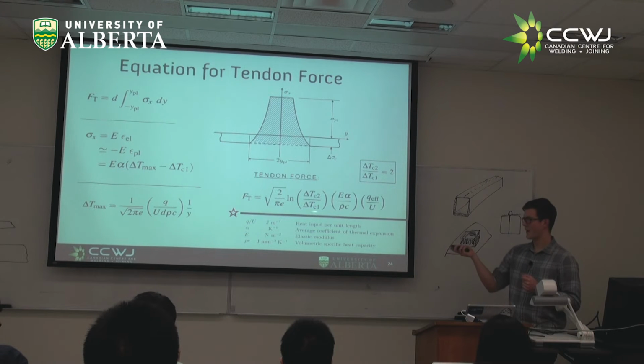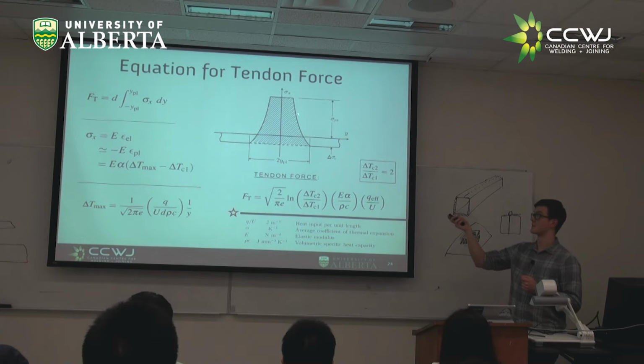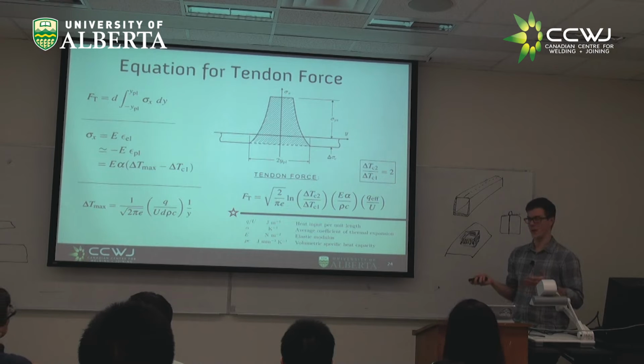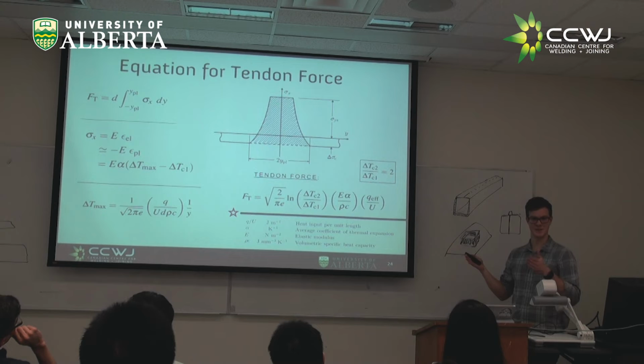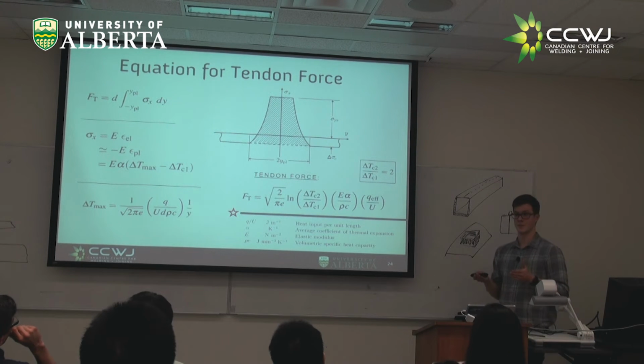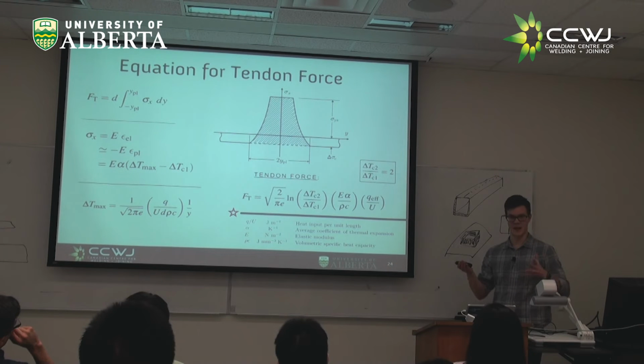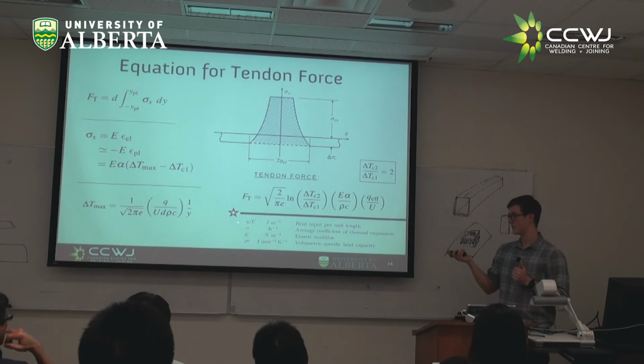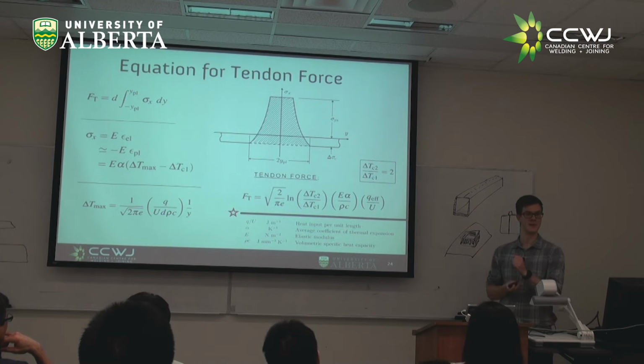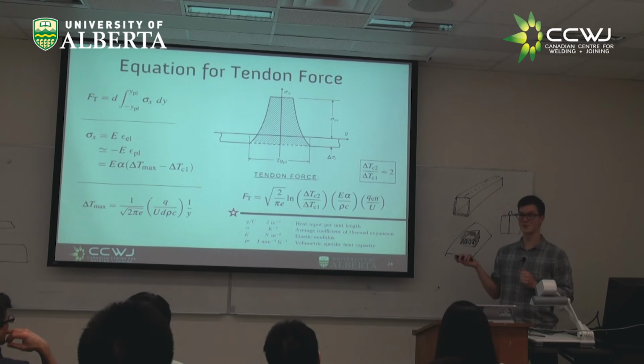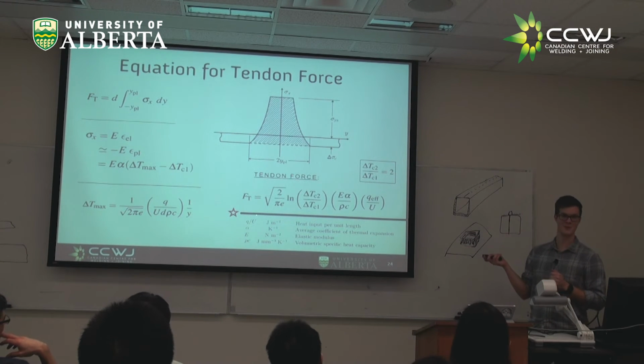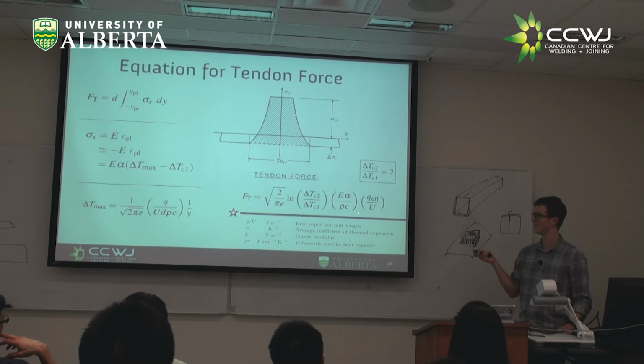So what's really powerful about this expression is that if we know the heat input, we know some material properties, we can calculate this integral of residual stress. And we can start to calculate how much we would expect something to bow, how much that compressive stress is going to be away from the weld, all sorts of really critical things for designing weldments, for designing structures that have welding. And all we need to know is our material properties and our heat input. Now there's something in here we don't need to know. Does anyone see what's not in here, which you might have expected to be in here?